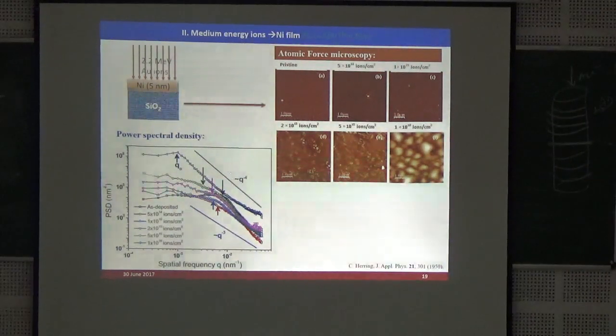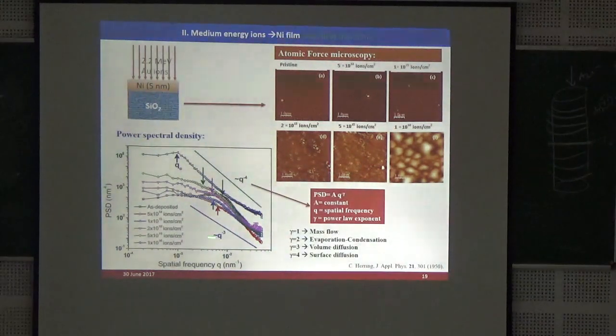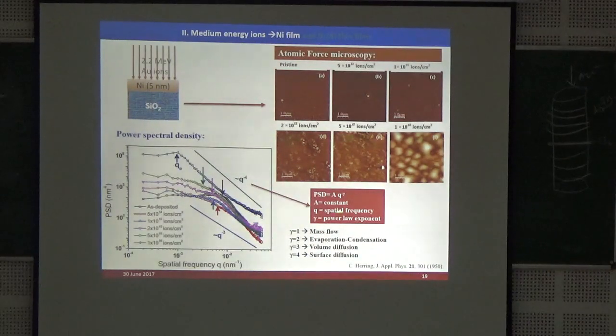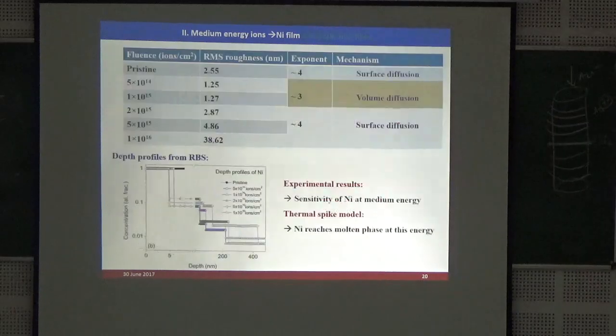So here you can see there are two regions. One is the plateau region, and then it sharply falls. This sharply falling region will give you the mechanism responsible for the growth. The PSD varies as a function of frequency according to this equation: A times q to the power minus gamma, where A is a constant, q is the spatial frequency, and gamma is the power law exponent. This power law exponent will give you the actual mechanism responsible. If gamma equals 1, mass flow was responsible for such evolution; gamma equals 2, evaporation condensation; gamma equals 3, volume diffusion; gamma equals 4, surface diffusion. Since we have seen mostly 3 and 4 dependence of the power law exponent in these cases, I have tabulated them here.